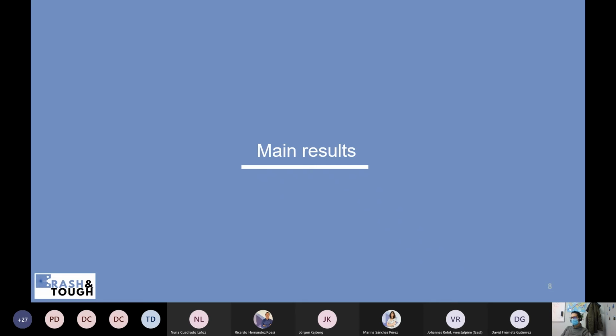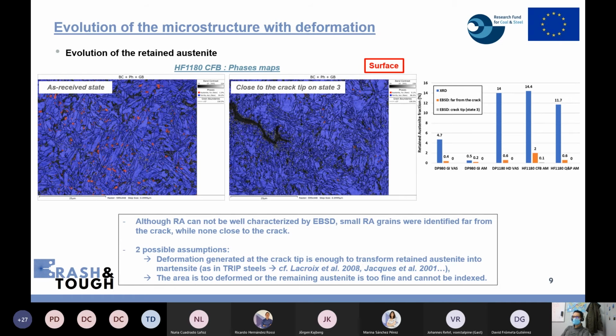Okay, so the main results. The evolution of the retained austenite. At each step, I only show the maps which come from the HF1180 CFB. And after, I will show you the quantified values. So what we can see at the as-received state, the state 0, we can see some austenite, but after the crack propagation, there is no austenite anymore,